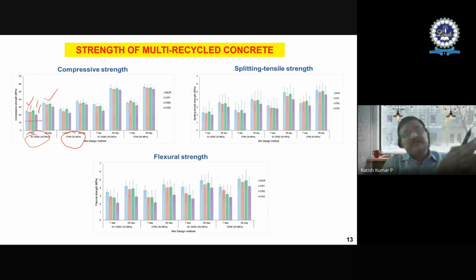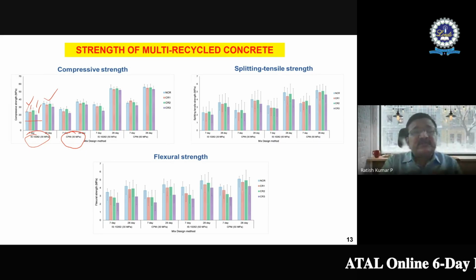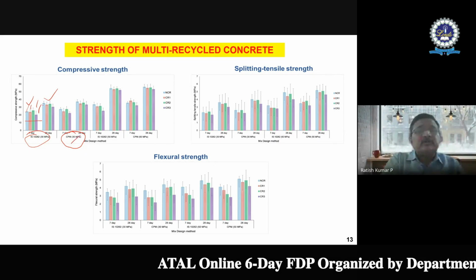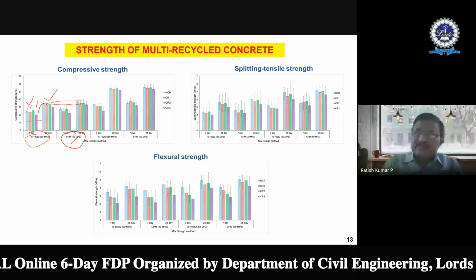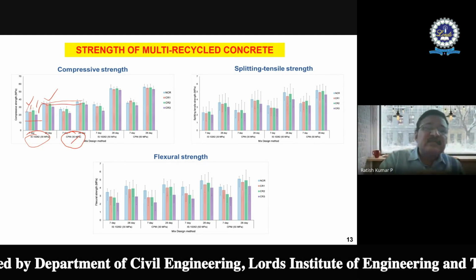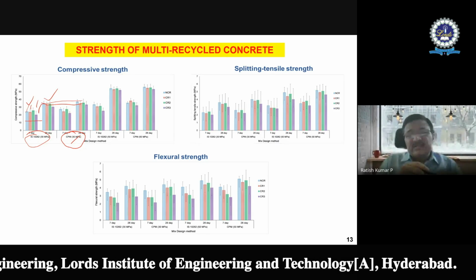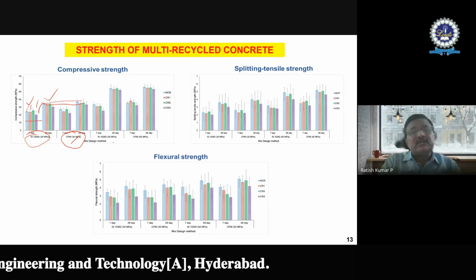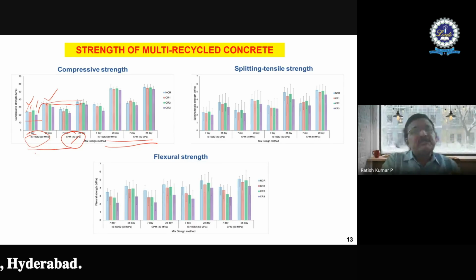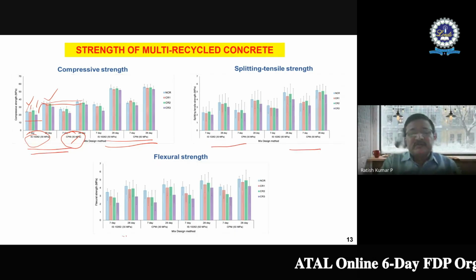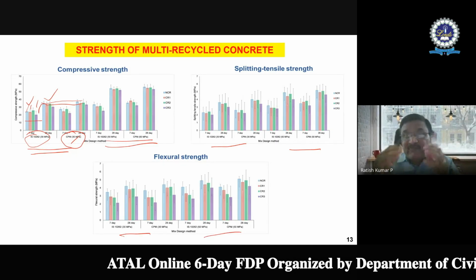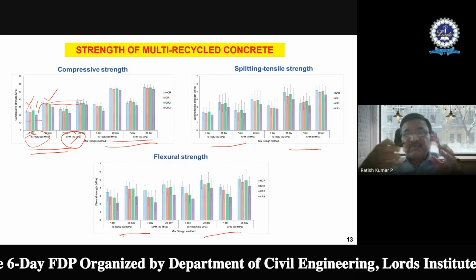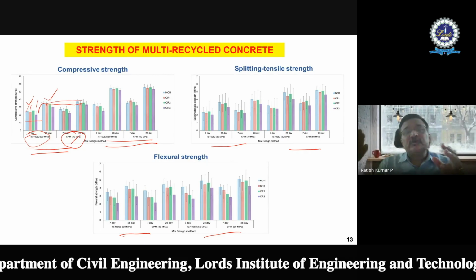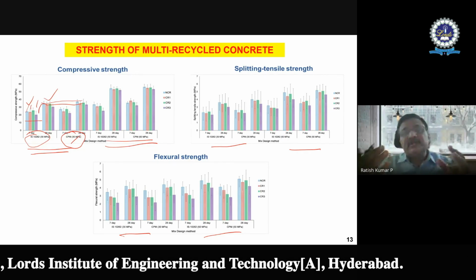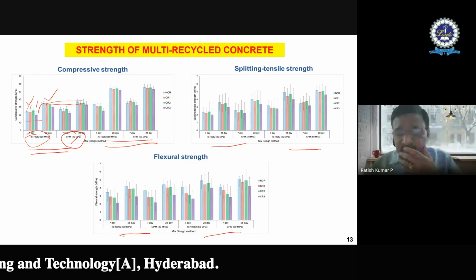So we could get a good benefit in terms of the CPM model, because you can see there's an increase in the strength, which means that with a lesser amount of cement I can still get the targeted compressive strength, which is definitely something good. I could get the same thing in case of 50 MPa concrete also, like 30 MPa concrete, and the same with respect to the split tensile strength and the flexural strength. That means by modifying the inferior type of aggregate, even if it is second generation or third generation, I get a benefit provided I'm using the right particle packing approach. So that is the point I want to make here.